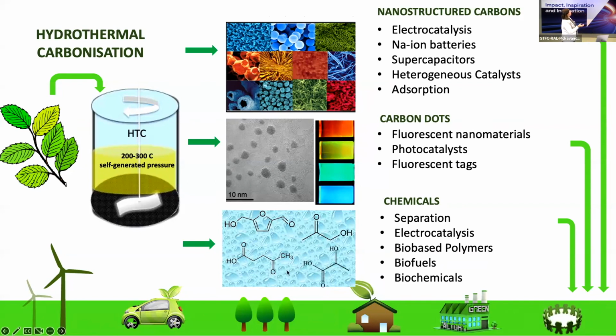While I was doing this, taking various biomass precursors, lots of pure ones but also real biomass, working a lot with cellulose and glucose, I was getting these black precipitates at the bottom of my autoclave. Rather than doing my job, I became fascinated by what this black stuff was and why it forms. In fact, it changed the course of my career because I realized that you could make carbon from dissolved precursors in water at only about 200 degrees, and you could shape and tune the morphology and the properties of these carbon materials.